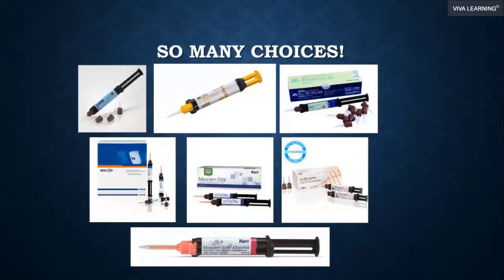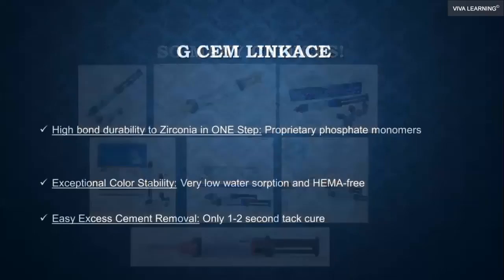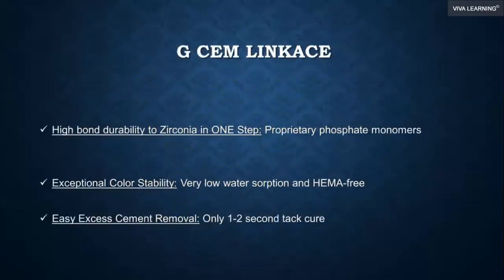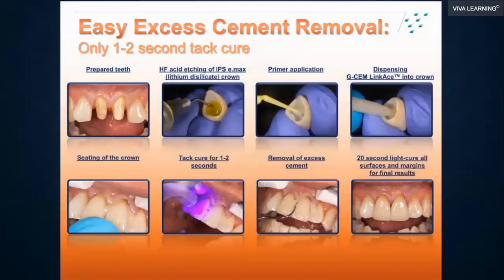Again, LinkAce is an ideal option in this space. With LinkAce, we have a high bond durability to zirconia in one step. We also have excellent color stability, and we have a simple way to remove the cement. Tack it for 1 or 2 seconds, and you can peel the cement off. So if you have good retention and good crown height, this cement will work well.